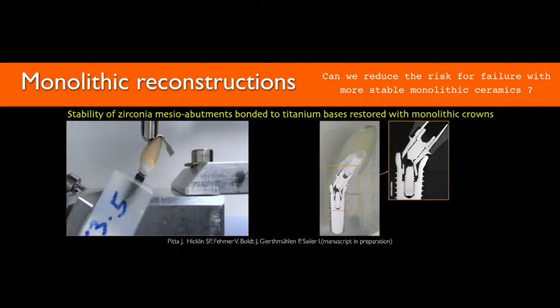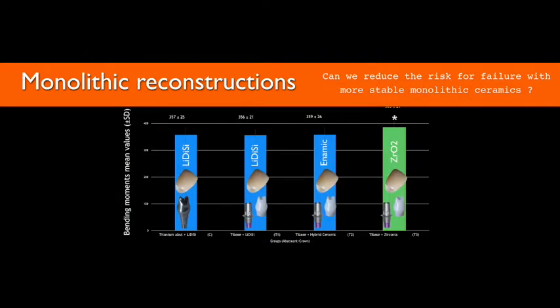Here you see the combination of materials after 1.2 million chewing cycles once we fracture them finally, and you see that there is a huge resistance in this material combination before they finally fracture, and here you see the ideal fracture in the screw head, and there we are with the final value. So what was very interesting for us is that even the combination of the hybrid material performed clinically very well in this in vitro study. You see here that the hybrid behaved with similar values to the zirconia combination as well as the lithium disilicate combination.